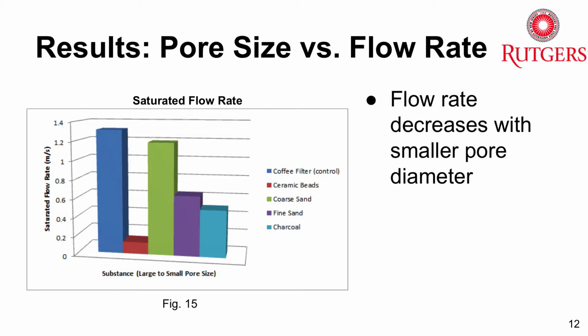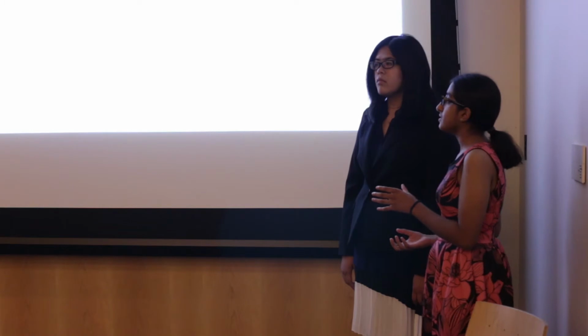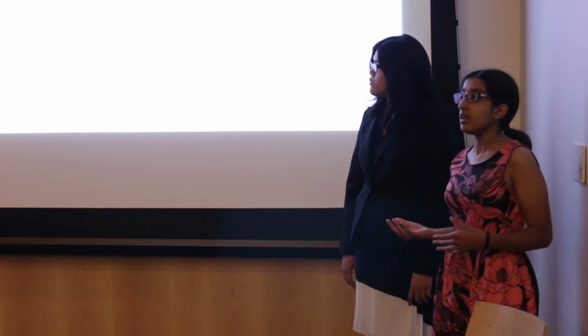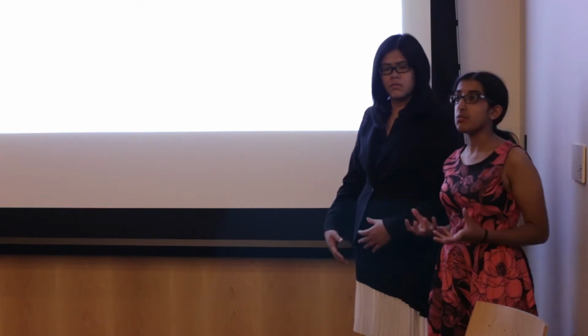The reason for this, we believe, is that although ceramic beads, in small or large amounts, have very large pore sizes compared to fine sand, ceramic beads also have a surface chemistry that interacts with water molecules through adhesive forces, and so attracts water molecules and doesn't let them fall through the filter very fast. We speculate that since the surface chemistry of the ceramic beads can affect how the water molecules flow through the mixed media filters, future chemical modifications to our hydrophobic aerogels could attract water molecules more and allow water to flow much more substantially through aerogel filters.